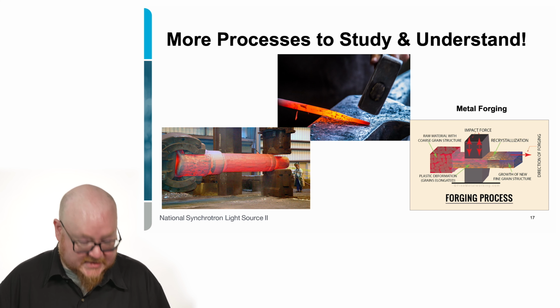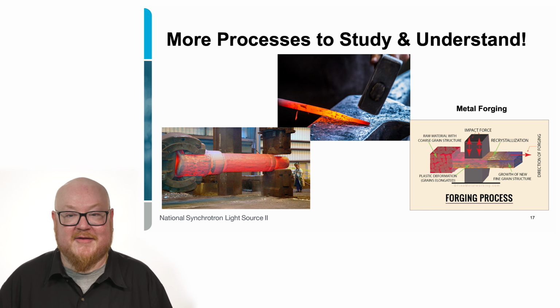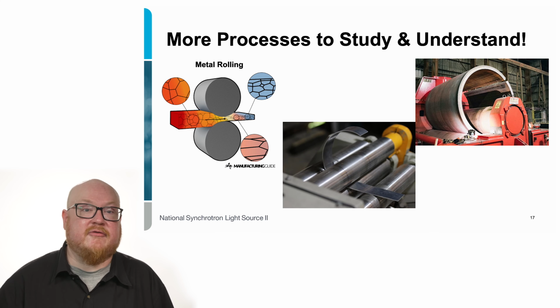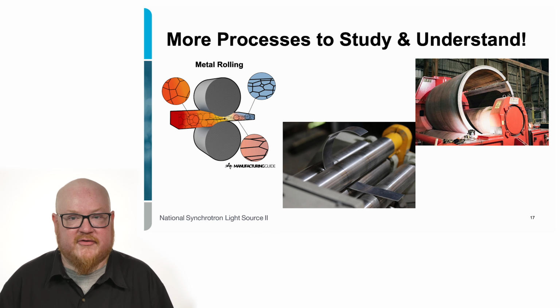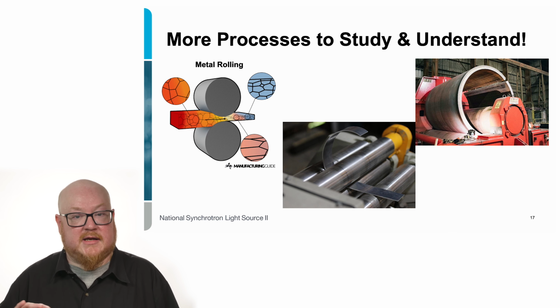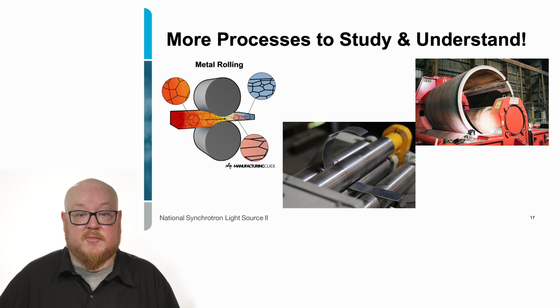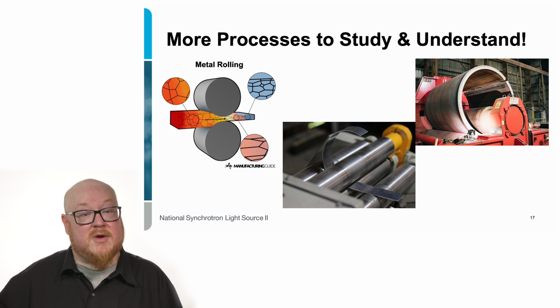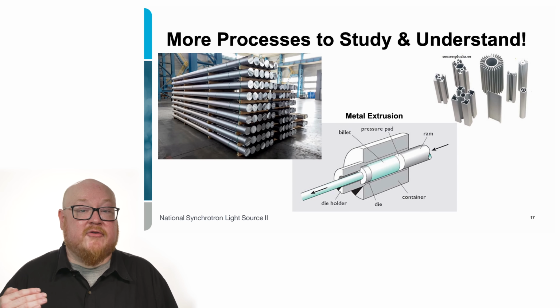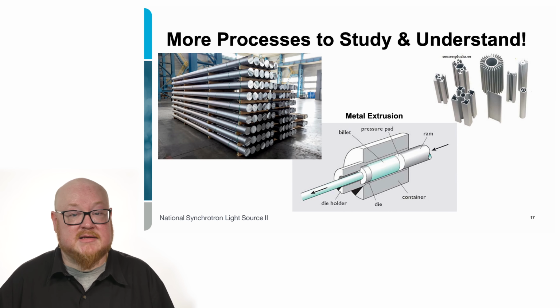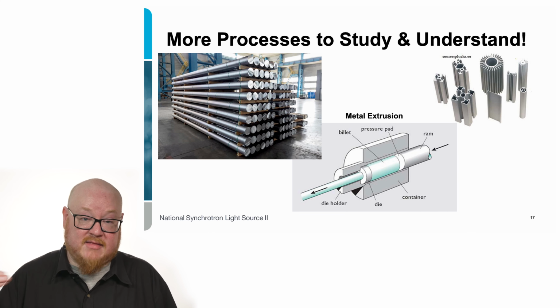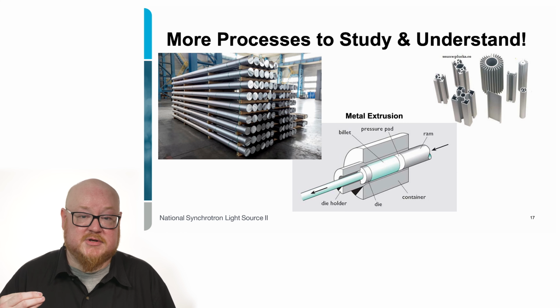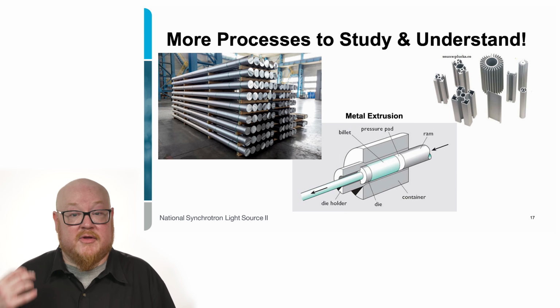And the great thing about this is that it's only the beginning of the study. We have so many more things to do where we can determine other conditions of forging, and we can also look at different processes of metal formation, such as metal rolling, where we take a larger metal and we roll it into a sheet in order to produce particular properties, where we can form sheet metal, or even, like shown on the right, large pipe fittings. And we can also begin to understand the extrusion process, where metal is forced through a die. And at that die interface, there are very high pressures and temperatures that are experienced, and we are able to replicate those at the NSLS2. So this is a very exciting field that we're hoping to continue looking into.